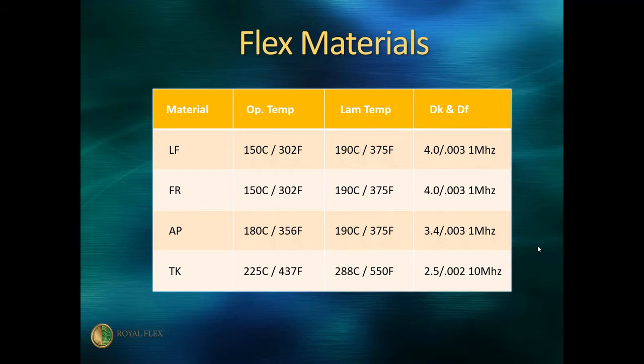We provide a lot of our customers with solder leveling and hand soldering versus the SMT assembly, and flex versus rigid flex. But the main thing we find is getting the moisture out of the board and then using a very easy curve, I guess to say, to get to temperature. If you rise too fast, you'll definitely get separation on flex if it gets too hot too fast.